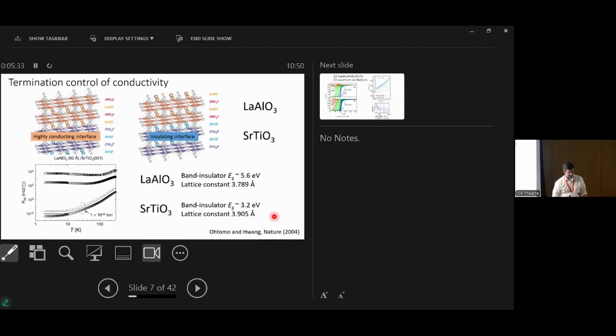So what he discovered a few years later is that if you take strontium titanate again, which is the most important character, and stack lanthanum aluminate on top of this material, these are two materials with very similar crystal structures, basically the same crystal structure, and very similar lattice parameters. So these Lego blocks are nearly the same size; they stack together. And nominally, they're both insulators as well. Lanthanum aluminate is a real rock. You can't make it conducting very easily. Strontium titanate, actually, if you dope it, like silicon, you dope that to become a conductor, you can dope strontium titanate to become a semiconductor and actually ultimately a superconductor as well.